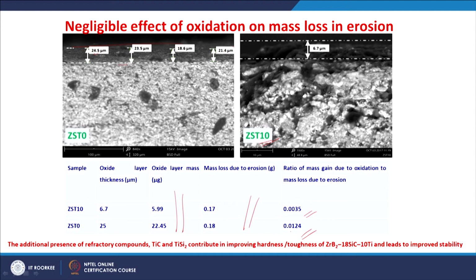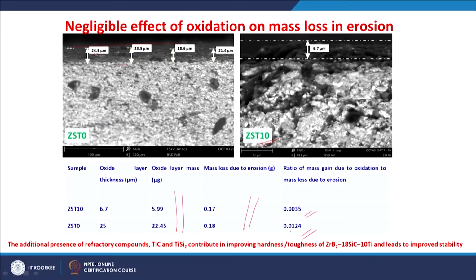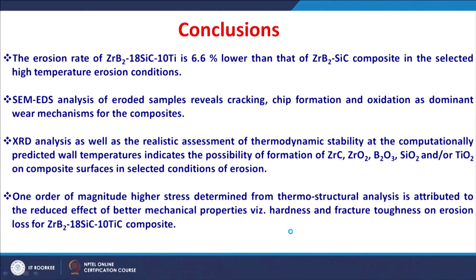So, we can also understand that the additional presence of the refractory compounds, for example, titanium carbide, titanium silicide, contribute in improving the hardness or toughness for the zirconium diboride silicon carbide titanium composite. So, it leads to improved stability. Finally, let us conclude the salient results obtained from this study. The erosion rate of zirconium diboride silicon carbide titanium composite is 6.6% lower than that of zirconium diboride silicon carbide composite.